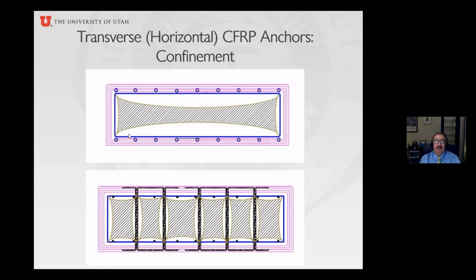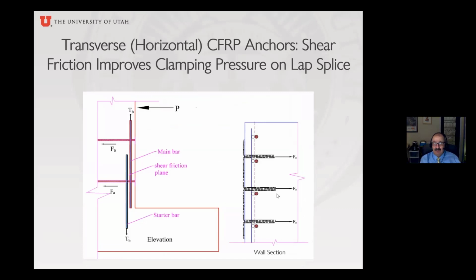So the confinement is very easy to see, because if you have a 4 foot by 1 foot wall and you go around it, your confining area is what you see shaded. But if you put these transverse anchors, now you're cutting that area into 5 pieces. So it's actually much more manageable, and it's much easier to confine the wall in the transverse direction this way. In addition, the anchors serve the dual purpose of putting confining pressure into the lap splice bars. And every time you have pressure here, when you put tension on these bars, it's much harder to pull them apart, because of shear friction that you're creating with this transverse pressure.